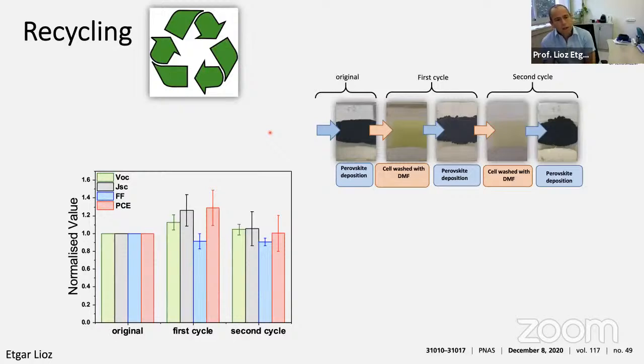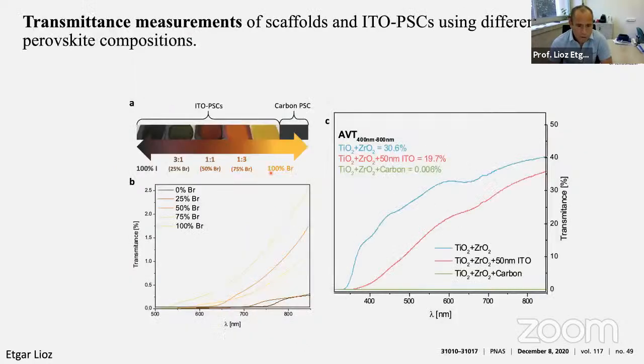And an additional property that we found out is that we can recycle the perovskite inside, which means the scaffold of these mesoporous metal oxide materials is very, very stable, which means that you can wash out the perovskite and then you implement a new perovskite and it's working almost the same as before. As you can see here, those are, for example, 2 cycles made from the fresh one, and then we wash, we dip it again, then we wash, we dip it again, and you see nicely how it works, which means that if you have some degradation of the material, this scaffold can work again and again as a full device.